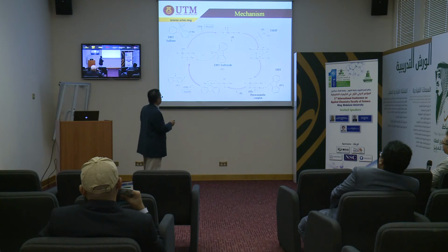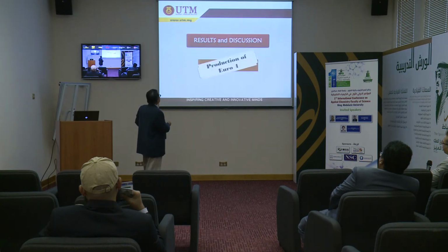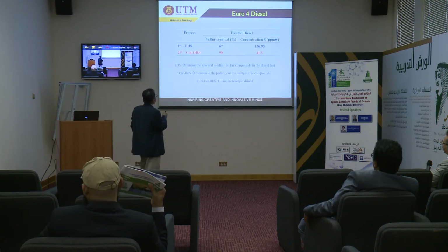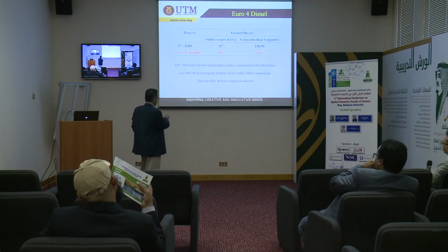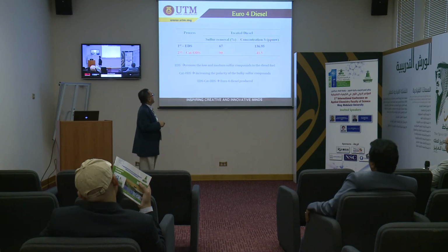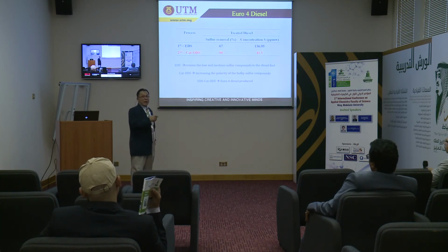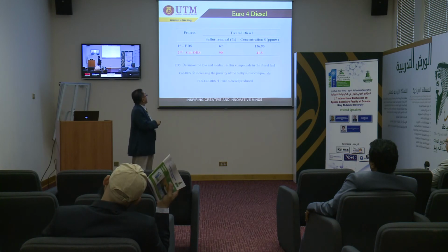Very simple mechanism. What we propose is that, to achieve Euro 4, there should be a combination. That means first we have to do extraction, secondly we have to do the catalytic oxidative process. Only then can we achieve this: sulfur compound from the original 415 ppm to 41.5. Okay, it's more than 90%.